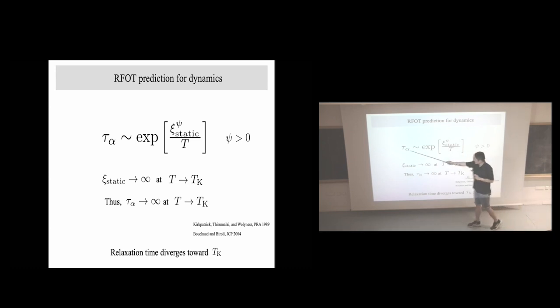Consequently, the relaxation time diverges toward the Kauzmann transition temperature. So it means that the origin of slow dynamics comes from the singularity of the Kauzmann ideal glass transition. So this is a very beautiful scenario. But in practice, we cannot reach the ideal glass transition, as I emphasized several times.